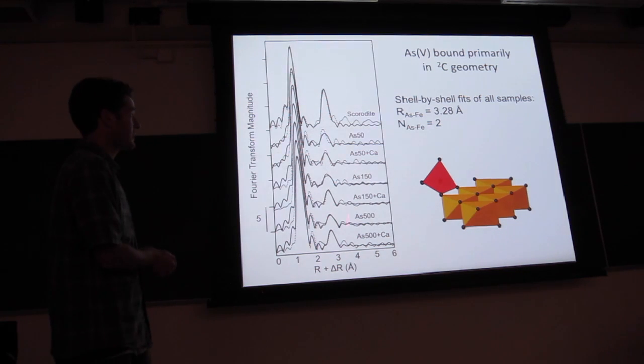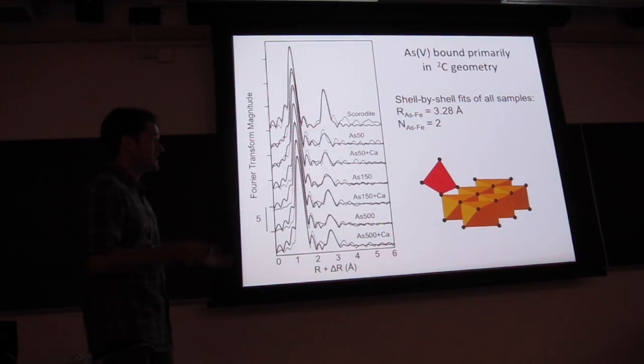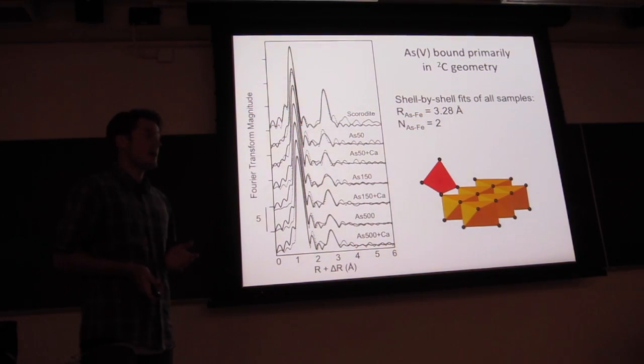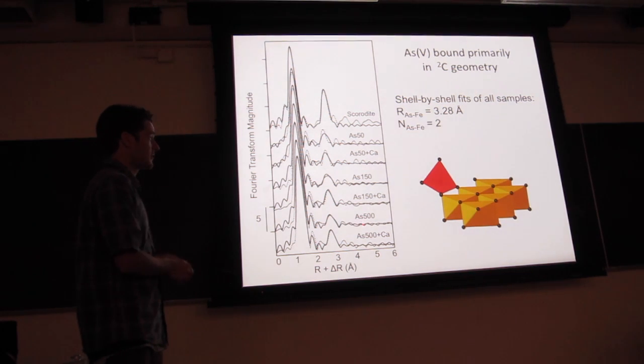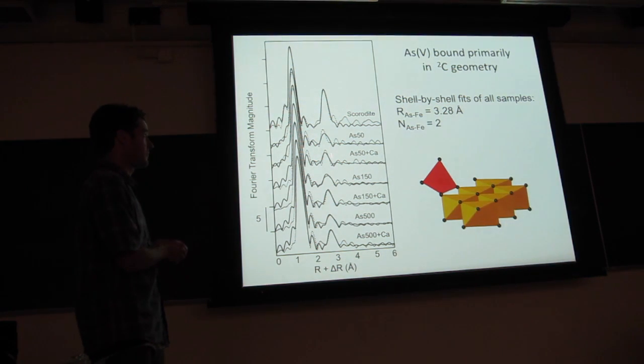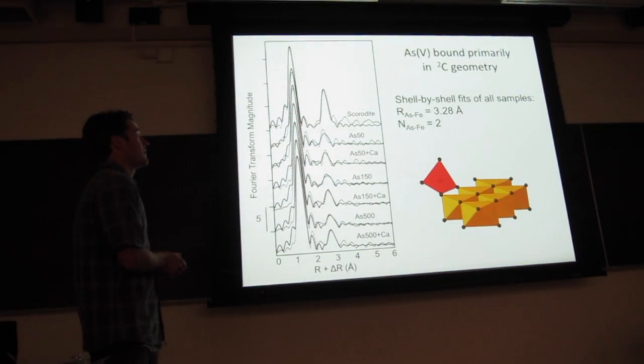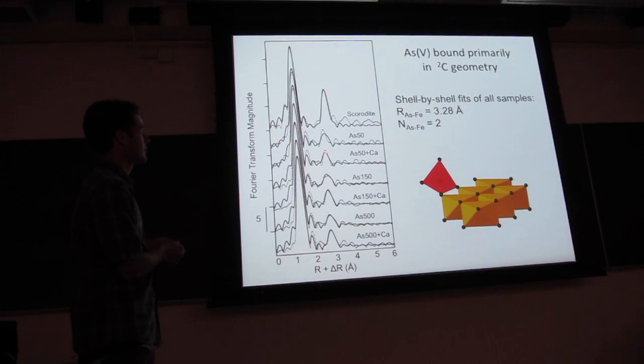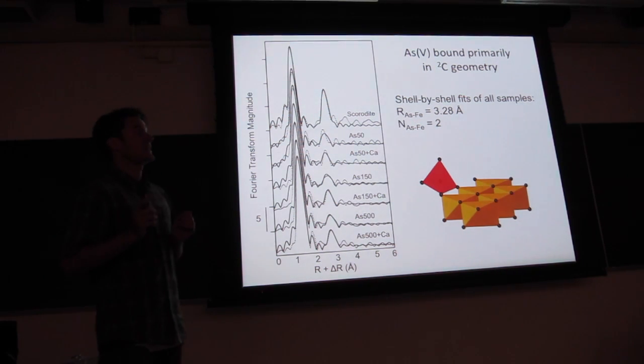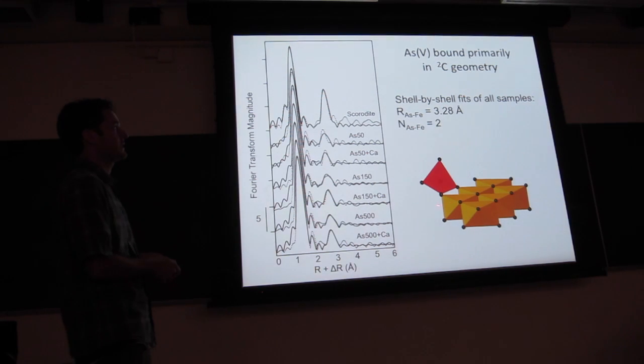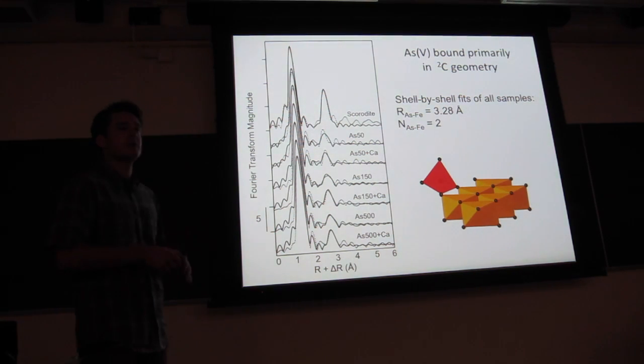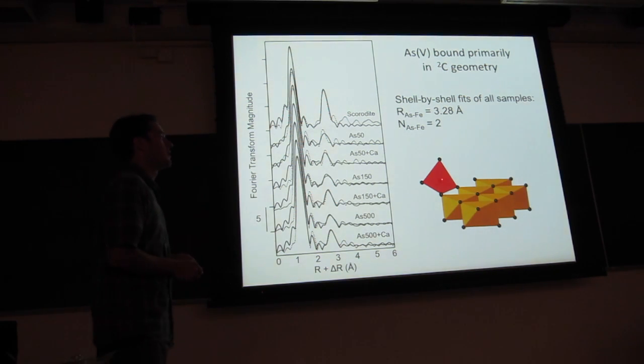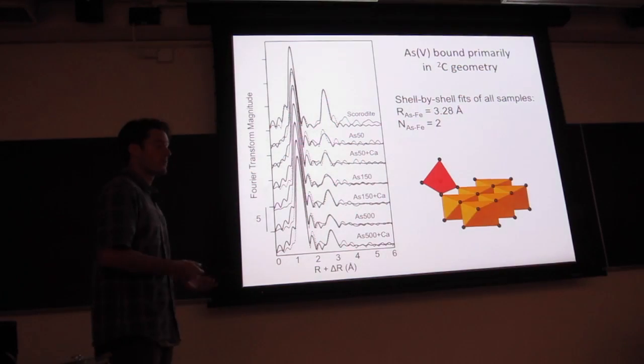Okay, so all of the remaining spectra are all of our samples. And it's pretty easy to see that all of our samples look pretty similar, regardless of the presence or absence of calcium and the initial arsenic concentration. And so we can actually model this second shell peak using X-ray absorption spectroscopy software. And the fits that we get, all of these peaks can be described by an arsenic coordination geometry with an arsenic iron interatomic distance of 3.28 angstroms, and an arsenic iron coordination number of 2, which is consistent with this configuration here. Arsenic 5 bound primarily in this 2C corner sharing geometry. And in fact, this is the primary arsenic coordination geometry to iron oxyhydroxides that's reported in the literature.